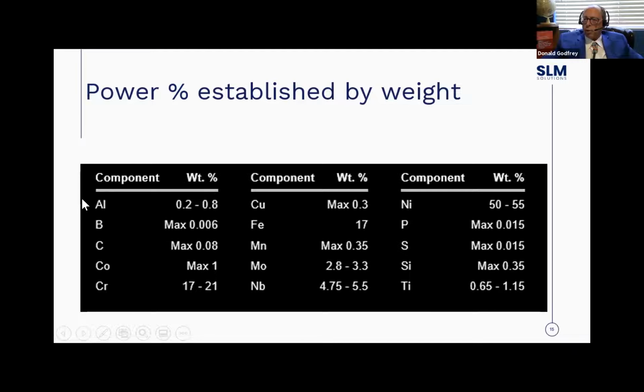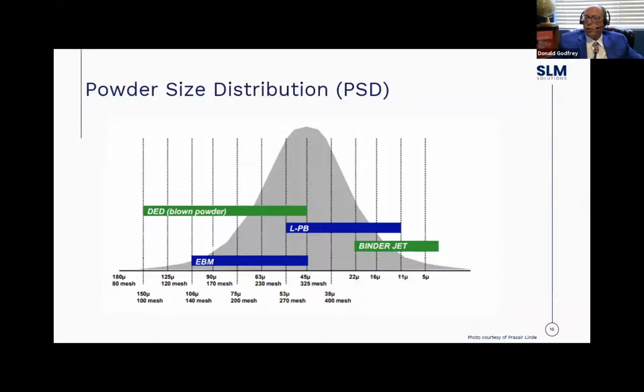And you're going to see your aluminum, your boron, your copper, chromium, iron, and they're going to have a bucket of iron there, and it's going to be 17% of the total weight of all the buckets. And each one of these elements will have their own bucket. So after you atomize it, you get this 1,000 pounds of powder at the end.